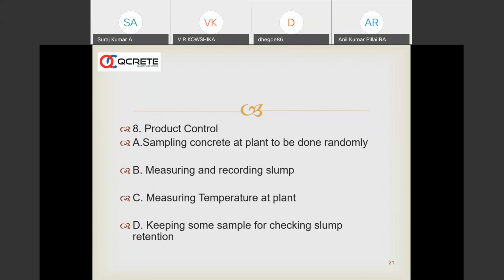For example, the concrete truck has to travel, let us say, 1.5 hours to deliver the concrete. So we take the sample at the batching plant, keep it for 1.5 hours, and observe how it behaves after 1.5 hours, especially with respect to the fresh properties. And cubes sometimes we take out of this concrete, which is kept for observation of slump. So these are the checks that we do as a part of product control.